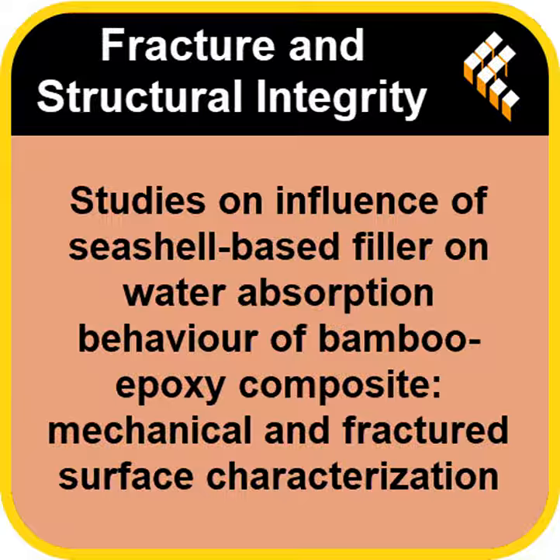Wow. So the mechanism is? The clamshell particles act as that barrier, reducing the water getting in. Less water means less fiber swelling, less plasticization of the epoxy, and critically, it maintains the integrity of that interface, allowing the composite to actually transfer load effectively even when wet. Okay, a 68% improvement in wet strength retention is, well, that's game-changing, isn't it?